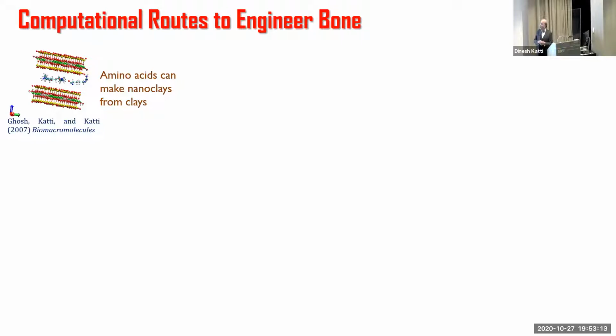Now, amino acids are biocompatible. Okay, so now we have clays themselves are biocompatible. So now we have nanoclays that are biocompatible. So we immediately remembered these simulations which we had done. Actually, in 2007, we published this work, and then we had just forgotten about it. We didn't even think about it. And this is one of those papers that had got a lot of citations, but we just didn't think much about it until we came across this problem. And so what we did was we took these nanoclays using unnatural amino acids. Instead of the natural amino acids, we decided to use unnatural amino acids because they are longer, and our simulations told us that it's better to use those longer amino acids.